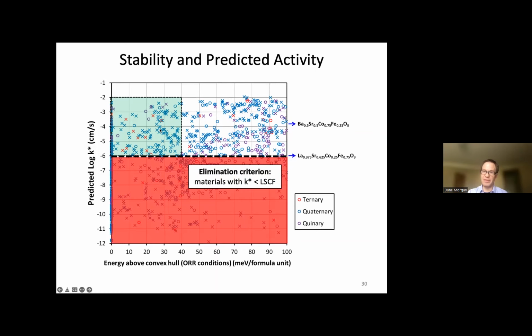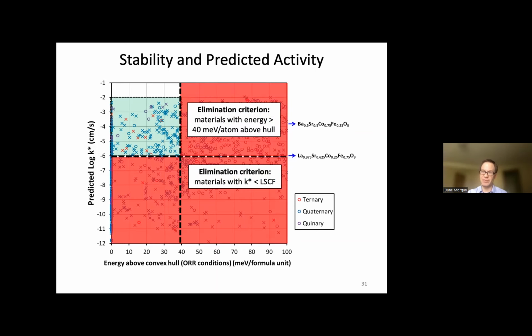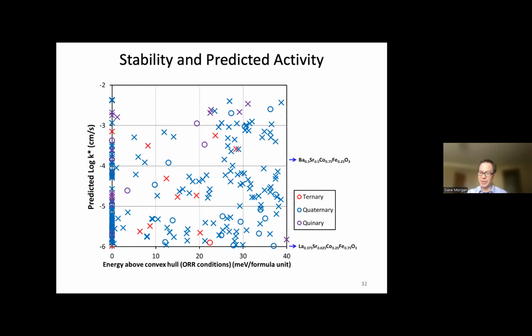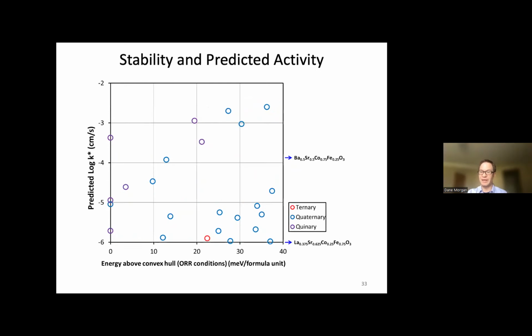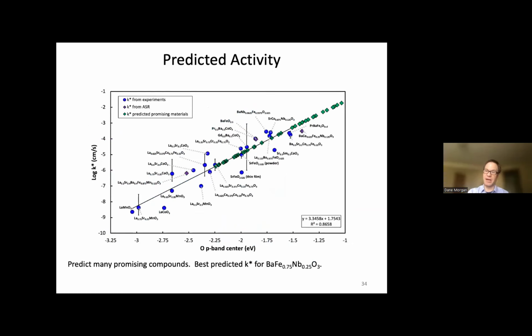So we basically got rid of everything that was too low in surface exchange coefficient. We get rid of everything that is too unstable. I can blow up this region. Then we got rid of everything that was insulating, and we get these remaining circles. So our 2,000 compounds became 20 compounds. Then we basically ranked those. I put them here on our K-star plot. All these green dots are our predicted surface exchange coefficients for a bunch of materials that we had never yet made. We just had computed predictions that they would be stable, good conductors, and have reasonably good surface exchange coefficient.